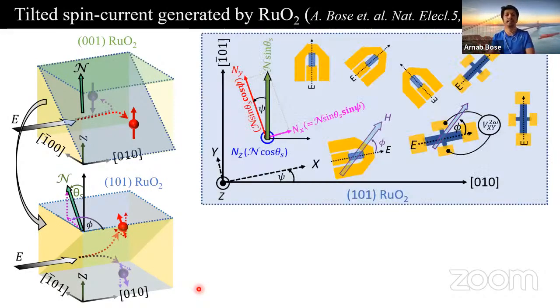Now for this, we fabricated devices such that we can run currents along different crystallographic axes, as shown here. And we are doing both STFMR and second harmonic Hall measurements. So here, note that in this plane, the Néel vector is canted, meaning it has projection in the plane and out of the plane. So it can generate out of plane spins when we flow current along the 010 direction. Now, if we run current along an arbitrary direction at an angle psi, then we further see the projection of the Néel vector along the current and perpendicular to it. Meaning we can have all the components of spin current, X, Y, and Z, but they will have a unique crystallographic angular dependence. So that would be the hallmark feature of this material.